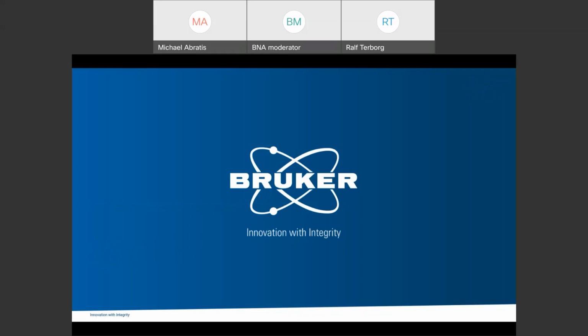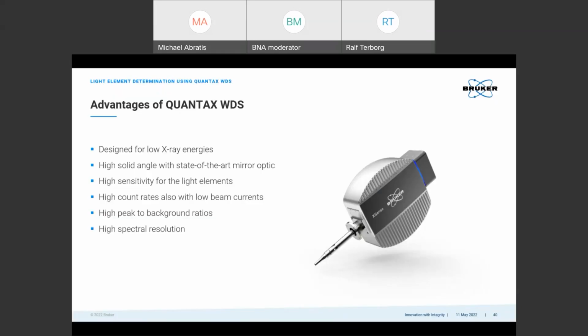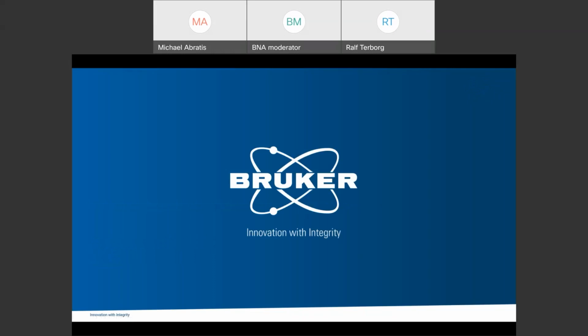With this, I would like to conclude. The QUANTAX WDS is designed with a focus on low X-ray energies, including the light elements which we presented today. With its parallel beam optic capturing X-rays close to the source of origin, the QUANTAX WDS has a high solid angle. In consequence, the QUANTAX WDS is very sensitive for the low energy X-rays. It can well analyze the light elements with low kV, low beam currents, and in low vacuum. Due to its higher peak-to-background ratio and higher spectral resolution, the WDS is an ideal complement to EDS. Thank you very much.